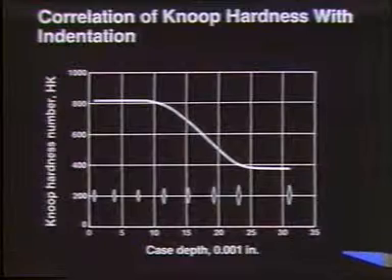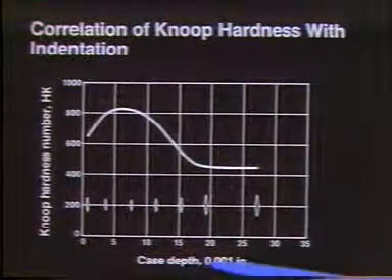Looking at the next slide, we see the effect of retained austenite on the surface. Again looking at Knoop hardness, you'll notice that at the very surface of the material, when we haven't penetrated very far, the material is softer than it is further below. That could mean we decarburized the surface, or something else. For this particular steel, if you cool it fast enough — if you pull it out of the furnace quickly enough — the surface can retain some austenite. So that soft surface condition is due to retained austenite, and then starting deeper in we have the standard drop-off we've examined before.